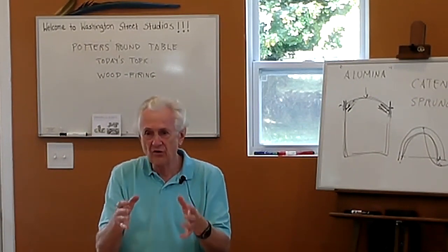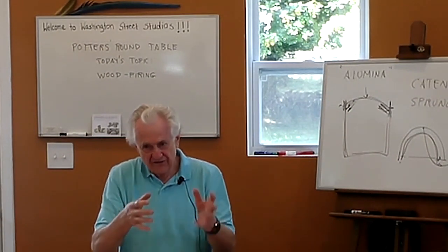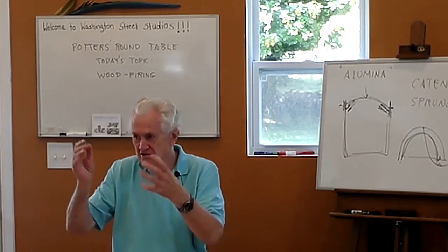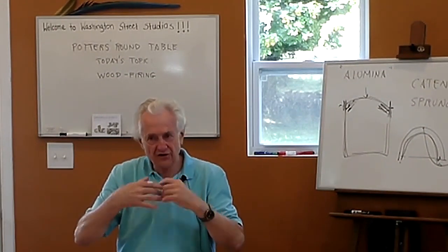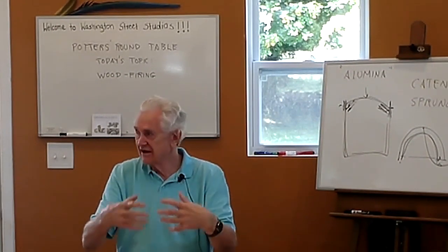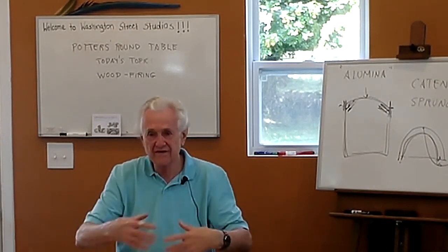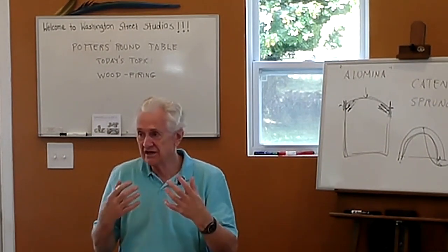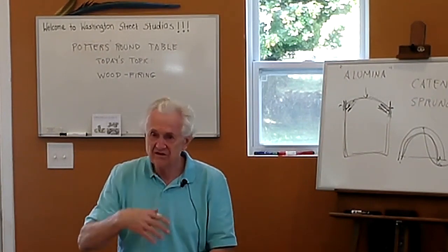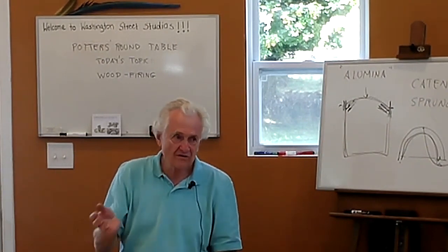It's the same way as if you have a fireplace. You need to start a small fire initially to start some hot air and gas moving up the chimney, to start the draw. And then as the draw improves, you can add more fuel, and as that burns, it gets hotter, you can add more fuel, and then the size of the fire can increase. But generally, you need some way to preheat the kiln. And depending on the kiln design, you may have to do more or less preheating.